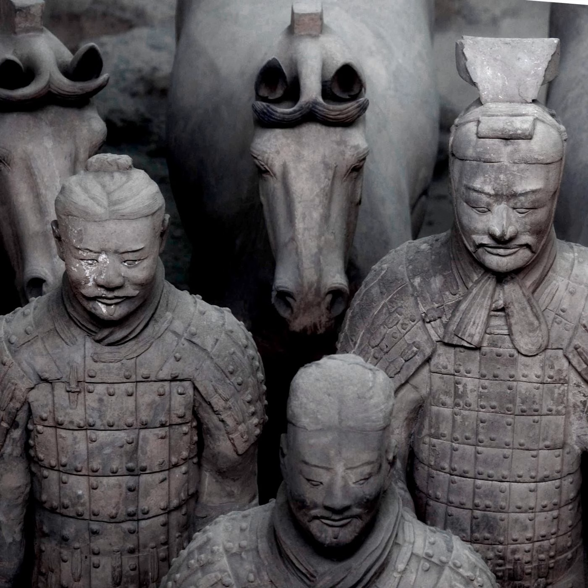Because let's say you have an undercut and you lose a chin or a finger or whatever. Well, it's just clay, right? So you can model a new clay chin onto your clay cast. And for larger mistakes, let's say you lose half a face or a shoulder. Well, you can just take some clay and press it into your mold piece, just the specific section that was lost, and then you basically create a replacement part that you can then attach to your damaged figure to repair it, right? So let's say you screw up the head entirely, but the rest of the figure is great.